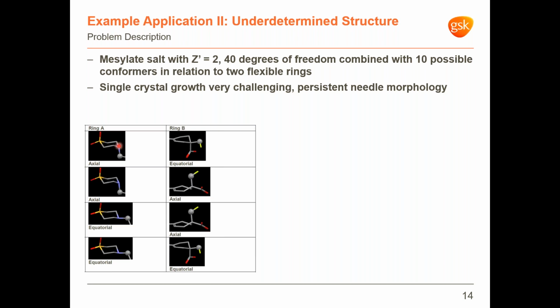Several efforts, I should say, of growing single crystals were unsuccessful, invariably resulting in very fine needles, which proved unsuitable even for synchrotron data collection. We did try very hard, and in this case, with no luck so far. So, starting with the process for determining the structure, in defining the 3D input model for the XRPD structure solution step, likelihood of possible conformers was also assessed from structures of relevant solvates and hydrates, which were previously known, and where the different conformers were actually observed.